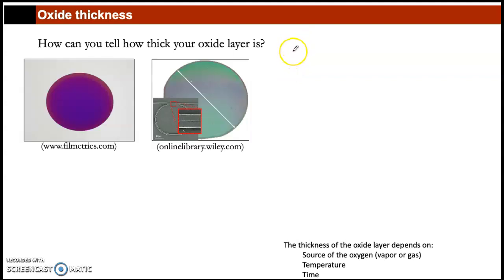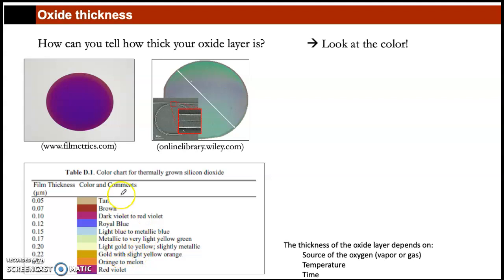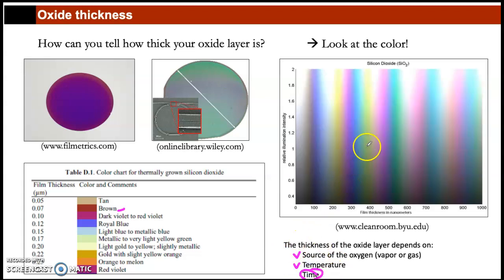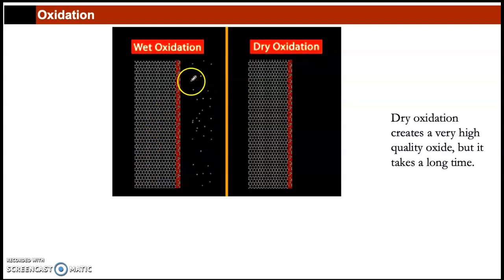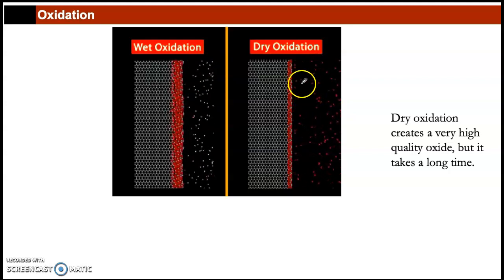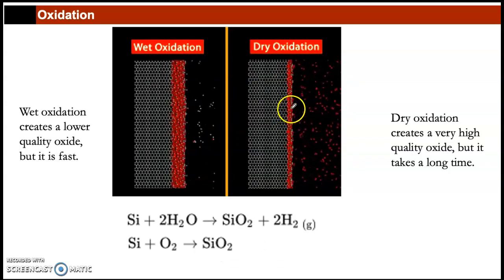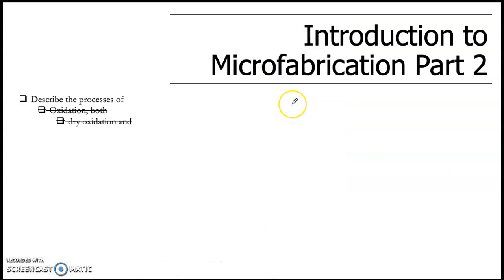You can determine the oxide layer thickness by its color. For example, a red-violet color corresponds to approximately 0.27 micrometers, while brown corresponds to about 0.07 micrometers. The thickness depends on the source — water vapor or oxygen gas — the temperature (800 to 1000°C), and the deposition time. In summary, wet oxidation is fast but gives low quality, while dry oxidation is slow but gives high quality oxide.